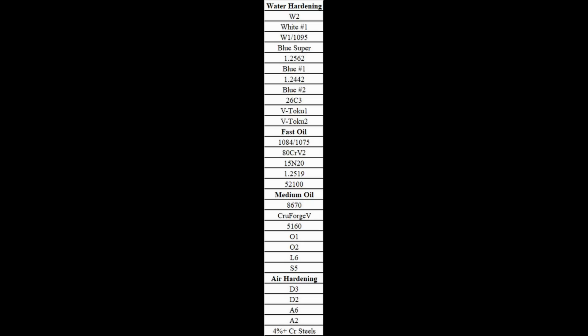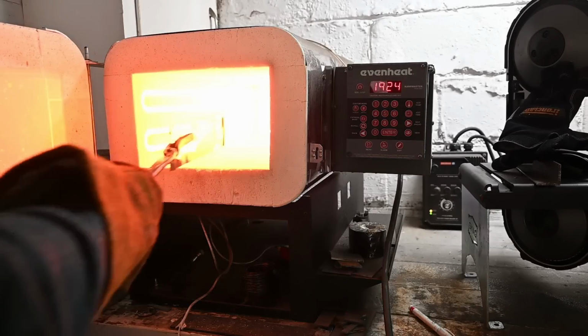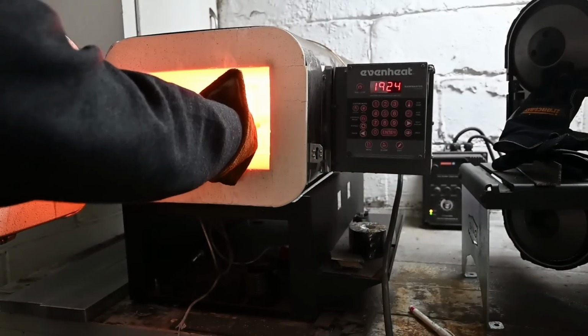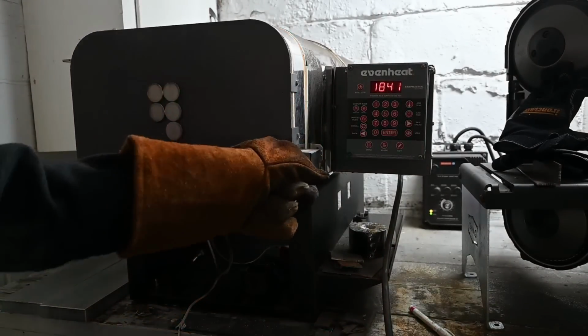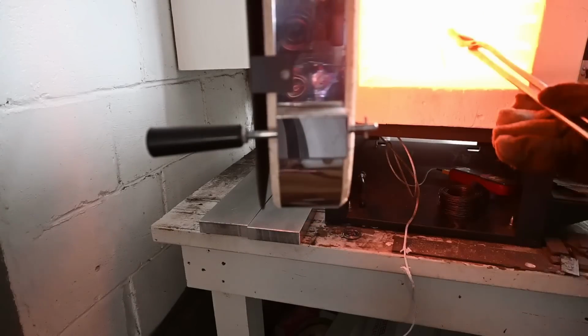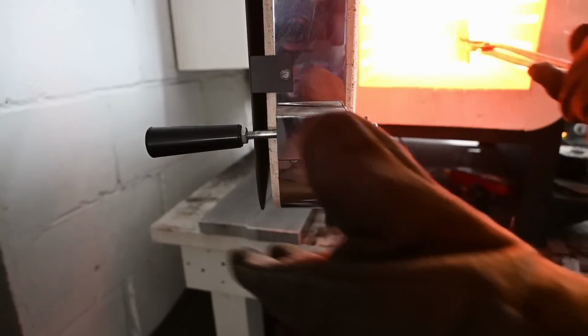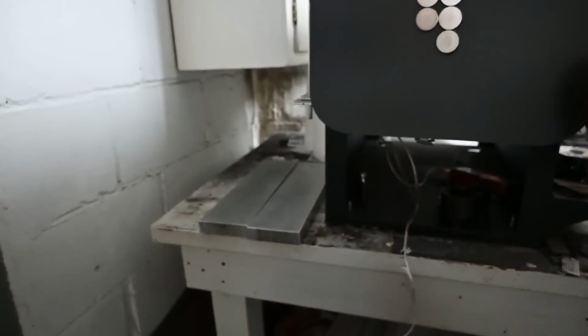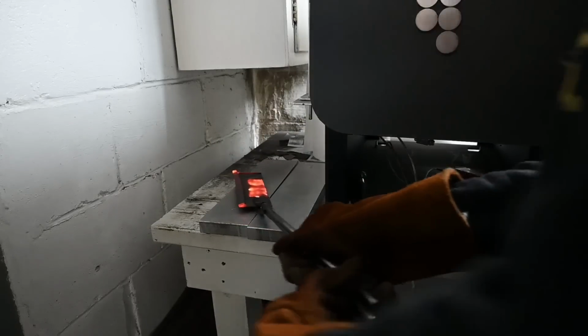Factory knives tend to use air hardening steels, in part because they are better suited to large batch heat treating, and in part because all stainless steels are air hardening, and stainless steels are more common with production knives. With custom knives, plate quenching has become popular in the past couple decades for air hardening steels. Plate quenching involves placing the steel between two plates, usually aluminum, and the plates draw heat out of the blade. This is faster than sitting in air and also helps maintain flatness during quenching.